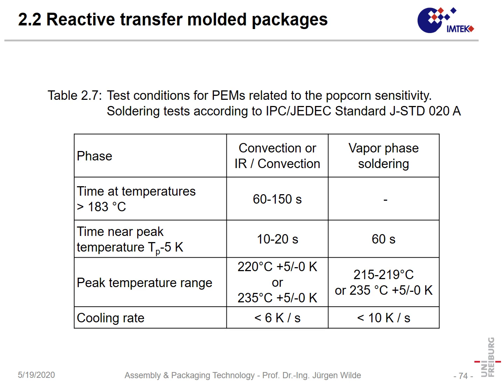For instance, in tin lead alloys, it describes the time at temperatures above 183 degrees centigrade, and in your test, this time must be between 1 and 2.5 minutes. The time near the peak temperature, that is the highest temperature you can measure in your oven, must be 10 to 20 seconds. And the peak temperature range is either 220 plus 5 minus 0 degrees centigrade, or 235 degrees centigrade plus 5.